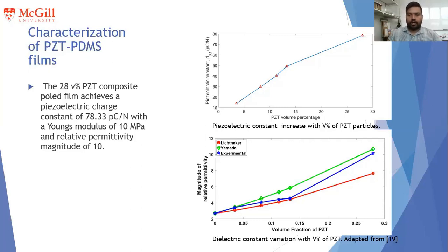We used an electroforce meter to apply a standard force across the film. The film is placed and the force is applied from the top. We also measured the dielectric constant, which we were able to achieve of 10 for the 28 volume percentage film.